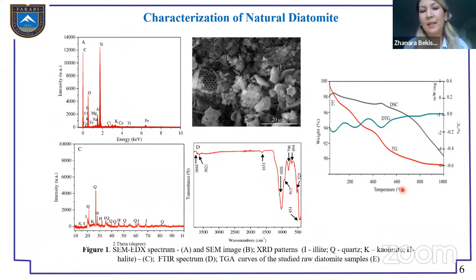Yes, sodium chloride is an impurity, a mineral halide impurity in the diatomite. A natural impurity. This diatomite contains this impurity, and after that, the formation of silver chloride, the reaction with silver, was brought about with sodium chloride in this halide, and after that, we reduced the amount of the silver which didn't react with the halide. All right. So some part of this halide reacted with silver, and some part remained. Which was the excess of the silver. For example, a small amount of the halide reacted with the silver, and the excess part was reduced with the hydrogen peroxide and metallic silver was obtained.